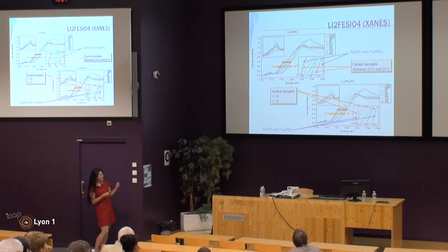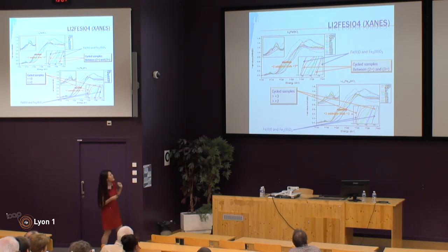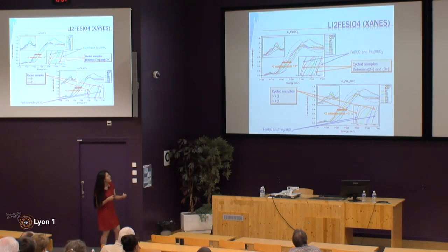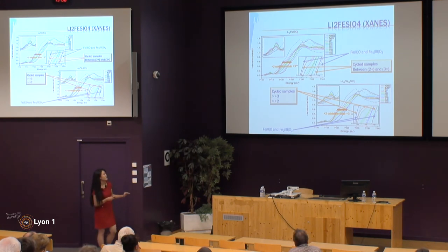When we put lithium back into the structure, we saw the doublet return, confirming the reduction of Fe3+ back to Fe2+. Looking at the normalised E0 value, we observed a clear shift to higher energy, confirming in-situ XANES evidence of Fe2+ to Fe3+ oxidation. However, the E0 value did not go further than the Fe3+ reference, so we believe we are not seeing any Fe4+ formation — consistent with both the standard and lithium-rich iron silicate materials.